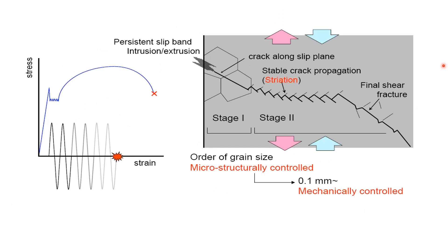And if you look at the figure here, we have discussed the stages involved in crack propagation many times in previous slides. So as you can see here, this is the first stage that indicates slow propagation along the crystal plane with high resolved shear stress and this involves just a few grains and has a flat fracture surface. And then we have stage 2 that involves faster propagation perpendicular to the applied stress, and we can see here that crack grows by repetitive blunting and sharpening process at crack tip, a rough fracture surface, and crack will eventually reach a critical dimension and it will propagate very rapidly.